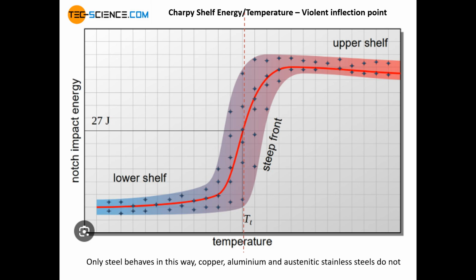And it's, in fact, the way in which the atoms are arranged that make it susceptible to this behavior. And so that's why you also have some of this behavior with duplex stainless steels, because you don't only have austenite, you have an austenite-ferrite phase balance. And that is why Charpies are required for weld procedure qualifications for duplex stainless steels, because of this problem in the ferrite phase.